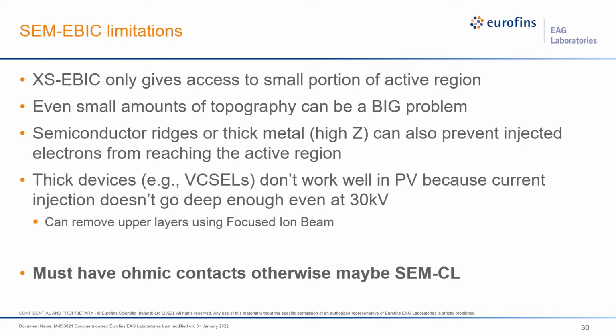And as I mentioned, even small amounts of topography can become a big issue. So if you have a very rough surface, you're going to have very different thicknesses of the material above the active layer. This can be a really big problem to try to actually discern where a defect might be versus just a change in topography.